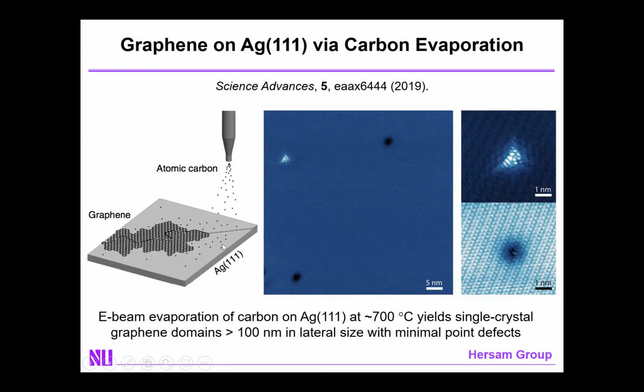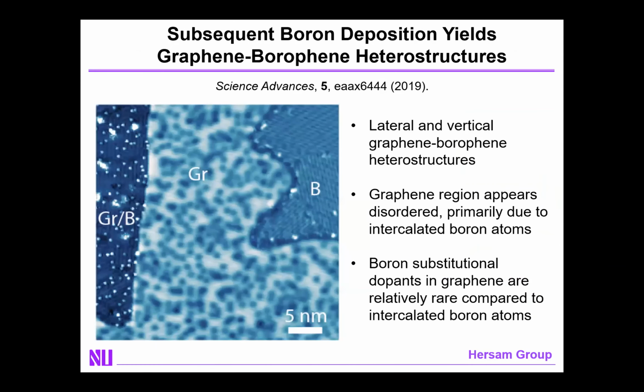a suitable growth temperature. And it turns out that to grow graphene, you have to go to a higher temperature than borophene, and that temperature is about 700 degrees C. And nowadays, after refining this growth over several years, we can get almost perfect graphene with very few atomic defects, as you can see in this image here. The idea then is to grow a submonolayer of graphene and then switch over to the atomic boron source and grow the boron subsequently.